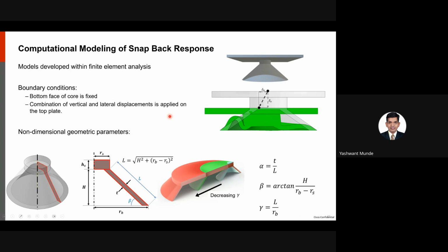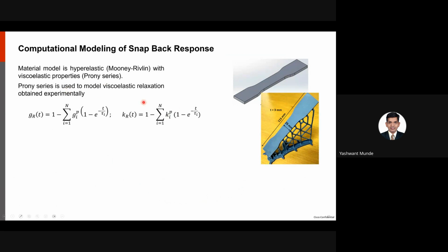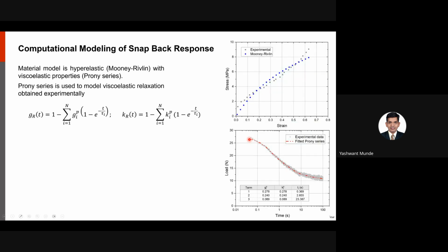So we modeled and simulated this in Abaqus. And the inputs to this were the viscoelastic response of these materials. So we used a hyperelastic Mooney-Rivlin model with viscoelastic properties as Prony series, as shown here. And the input to these were obtained by performing relaxation, that is tension, hold the specimen and allow it to relax. And we fitted that with the Prony series. And here's a response to show that these parameters for the Prony series do a good job at capturing that